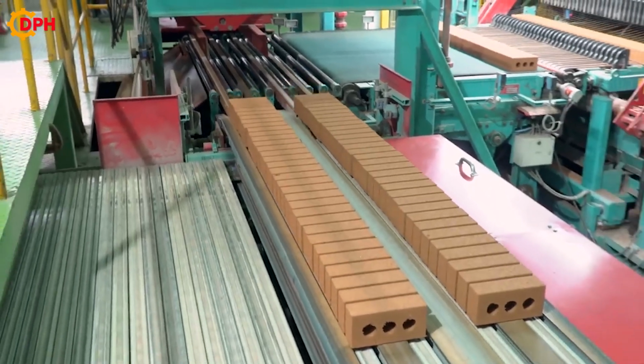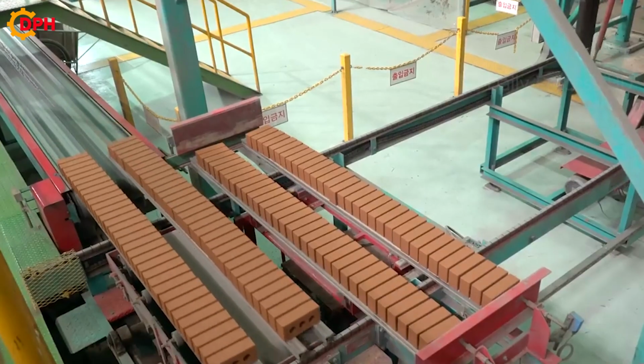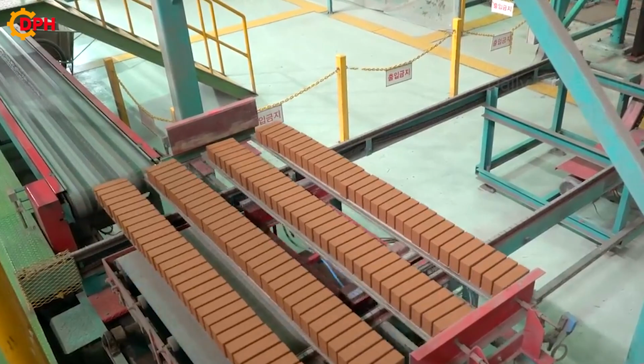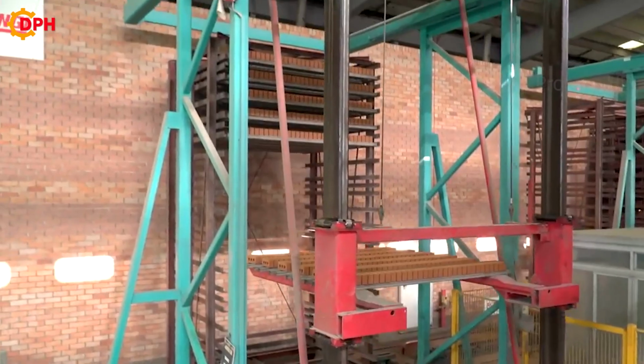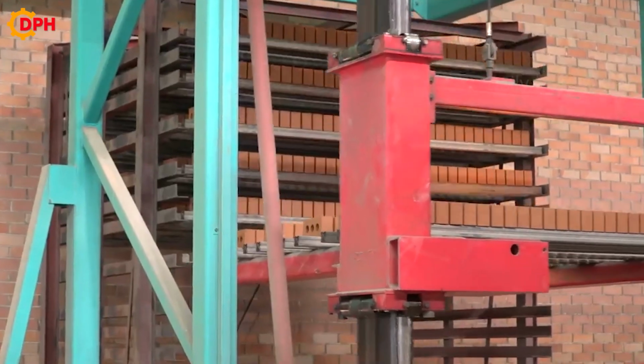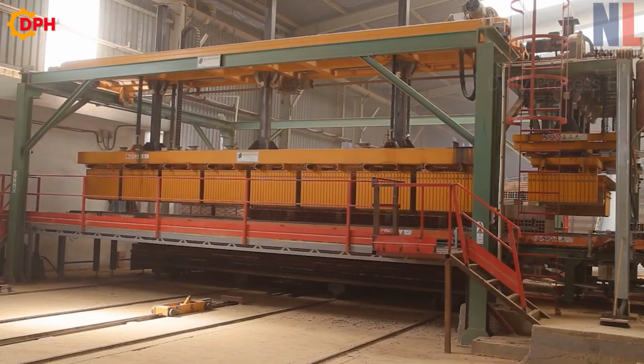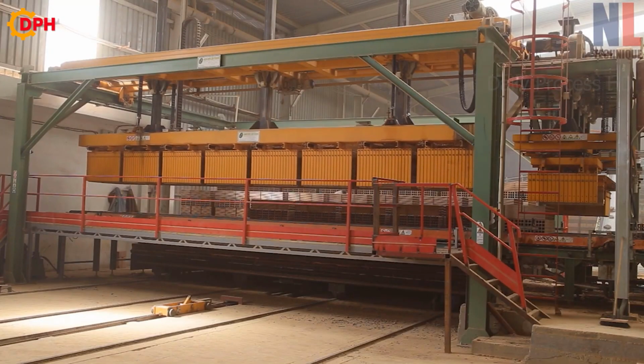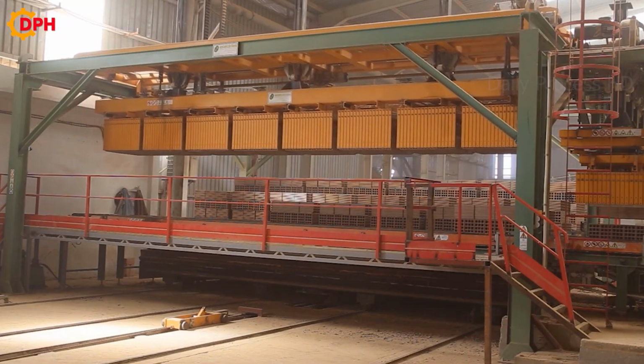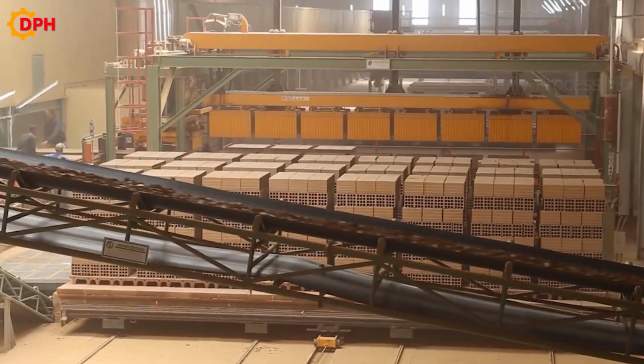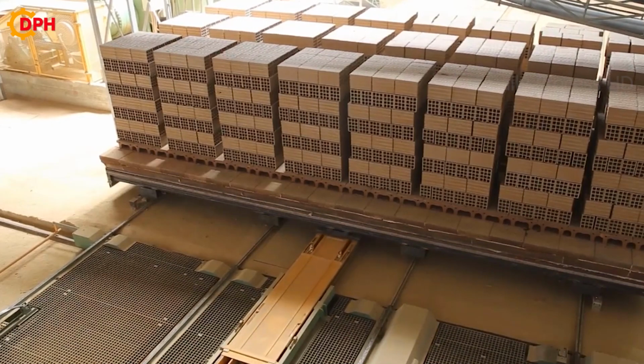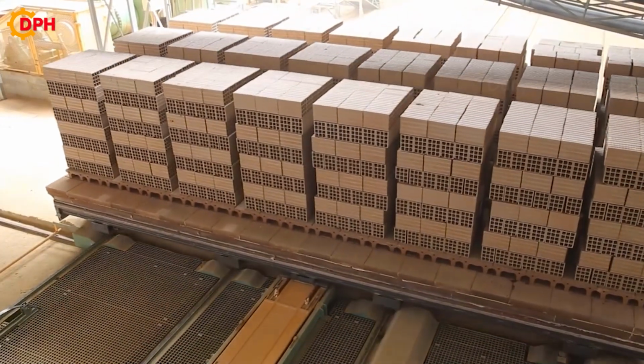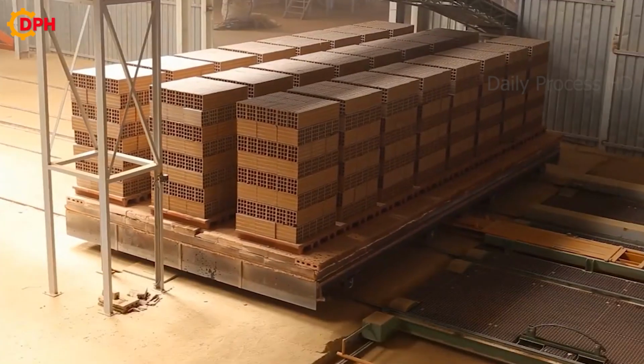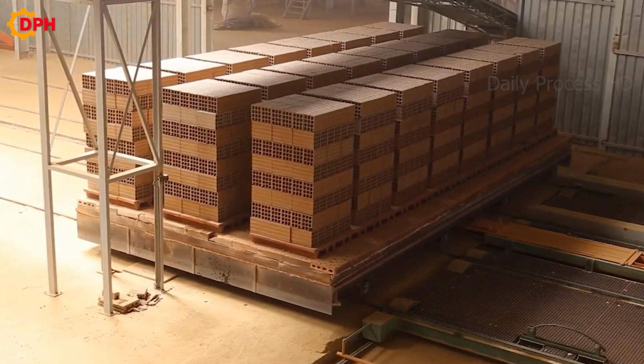After shaping, bricks are dried to remove water and increase hardness. The drying process can be done naturally or by machine. This is the most important step in the brick making process because if the bricks are not dry, they will be deformed when put in the kiln. The moisture content of bricks after drying should be below 10%. If the moisture content of the brick is too high, the brick will easily crack and break when fired.